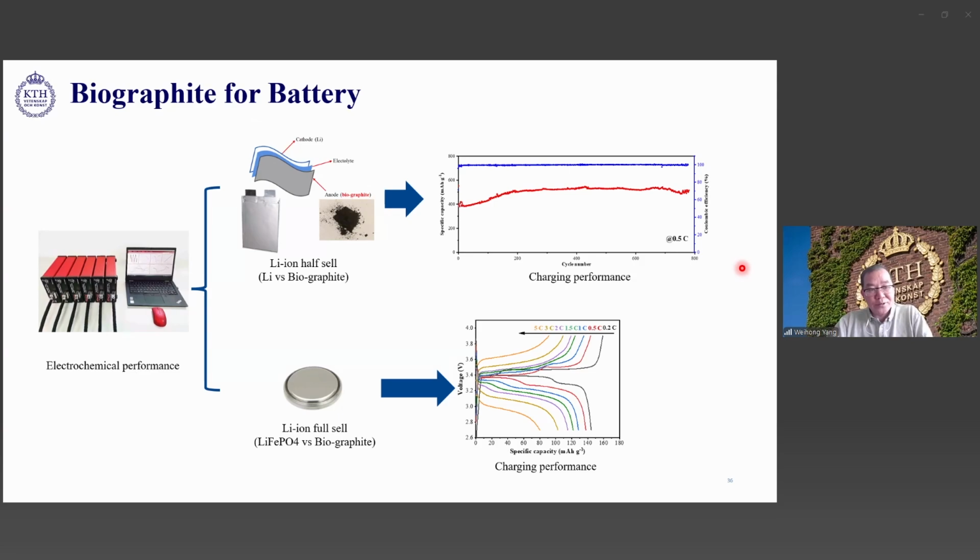That is the electrochemical performance, and you can see we can achieve a specific capacity of over 400 milliampere hours per gram of graphite, and this almost achieves the theoretical number that today's synthetic graphite is able to achieve. Also the Coulombic efficiency is 95 to 98 percent. It's very good, good enough compared to the commercially available graphite.